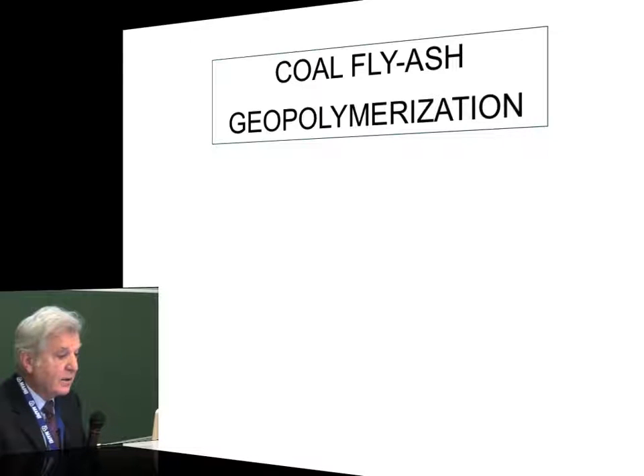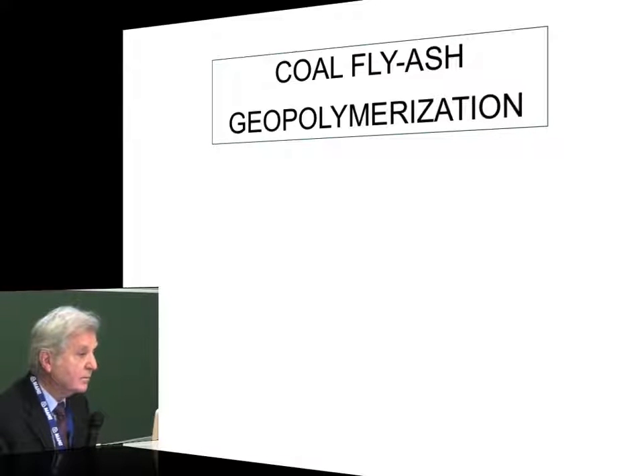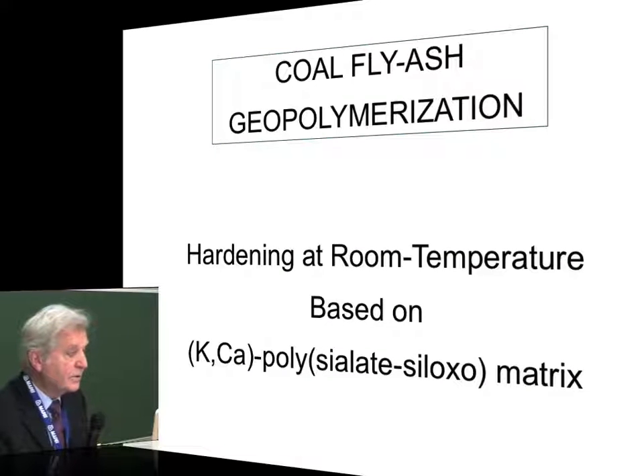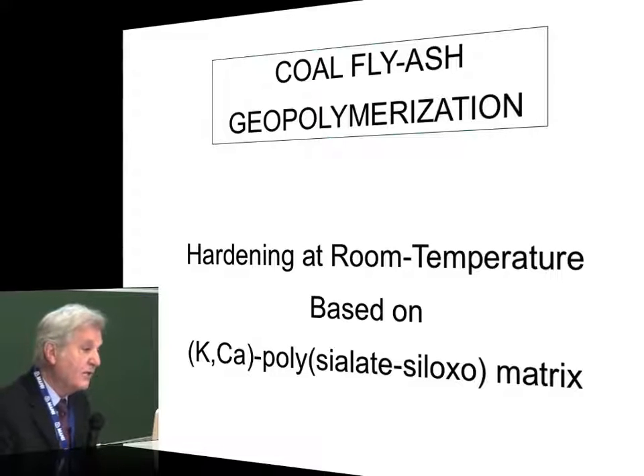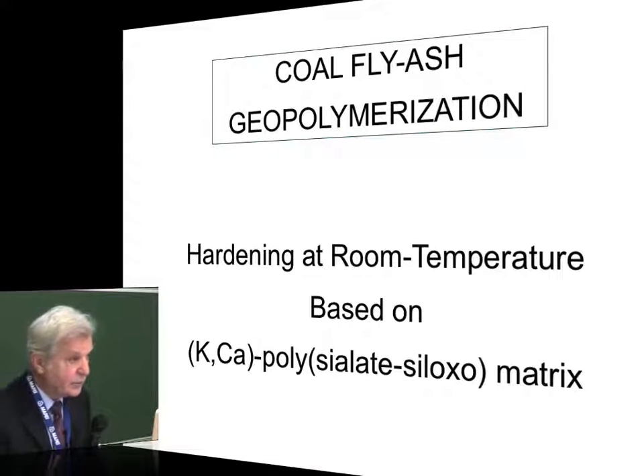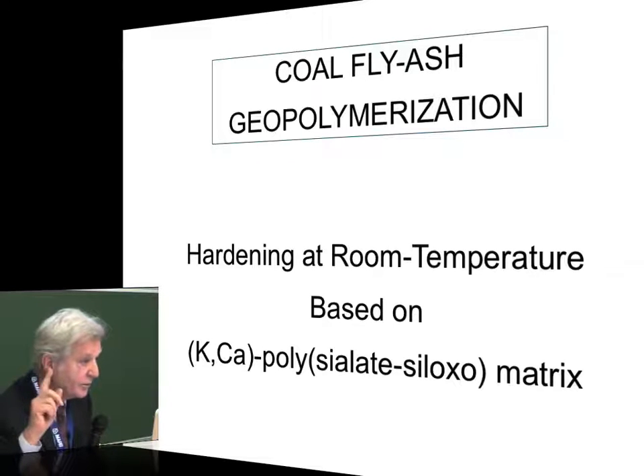So we have to cope with coal fly ash geopolymerization. But not at 60 degrees C, not at 85 degrees C, and so forth. It must be a cement. For me, a cement is something that hardens at room temperature. Otherwise, it is something different. It is a binder, or it is a resin, but it's not a cement. So any system that requires elevated temperatures is not. Well, they say fine, for precast, good, but this is not what we are looking for. We want mass production. Remember, we want to save the world.